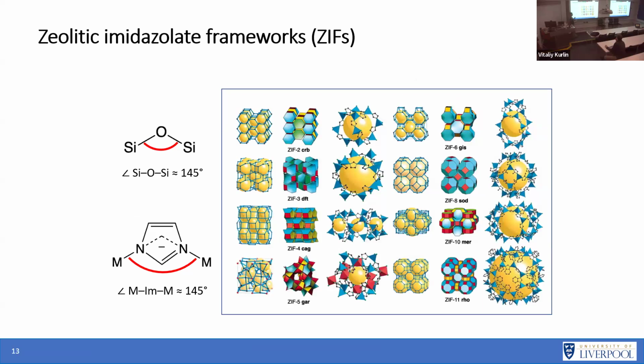So this then leads us to another class of metal organic frameworks, this time called zeolitic imidazolate frameworks. So these are materials that have got a zeolite type topology. So they are still metal organic frameworks, but they're a subclass of metal organic frameworks. You may have heard of these before, I'm not 100% sure. So in a zeolite, which is a purely inorganic structure, an aluminosilicate porous material, you've got this silicon-oxygen-silicon bridge, which has an angle of about 145 degrees. These zeolitic imidazolate frameworks have got a similar kind of angle, so between the metal, the imidazole, and the metal of about 145 degrees. So we define them in terms of having zeolite type topologies. So they would be described as having, say, a sodalite topology, etc. So they're a little bit like zeolites in that respect.